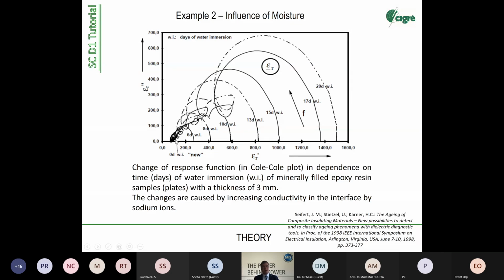That means in the interfaces or between the interfaces of the material, you already get a kind of space charge or space carrier effect accumulation. So the material is aging. Also from outside, it looks like it has not changed. So you see with this method, you can clearly see a change in the material. And by the way, these methods are non-destructive.